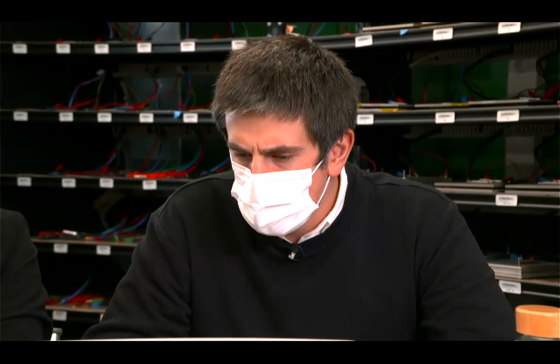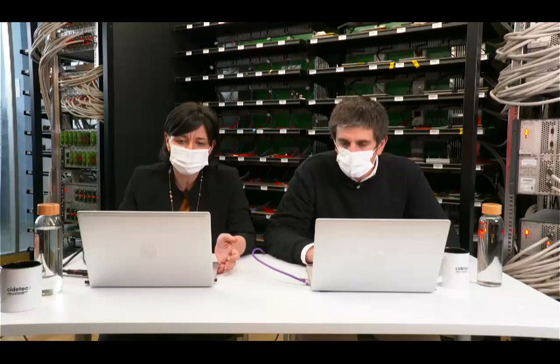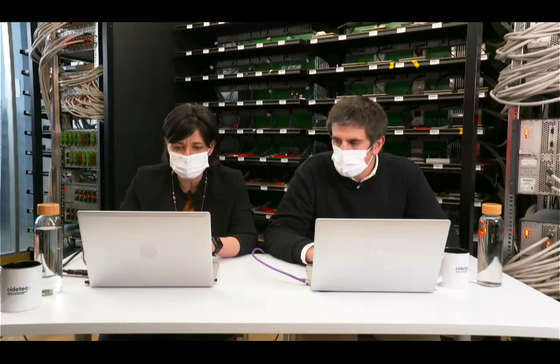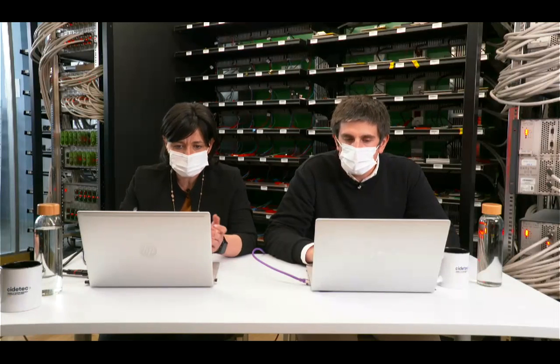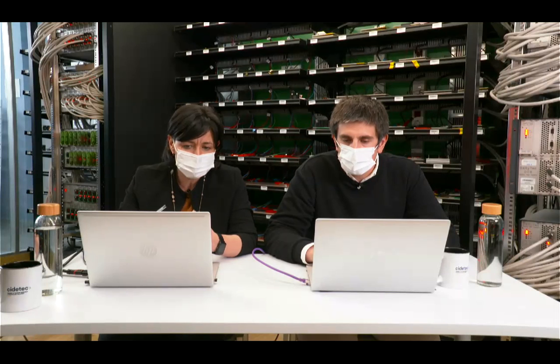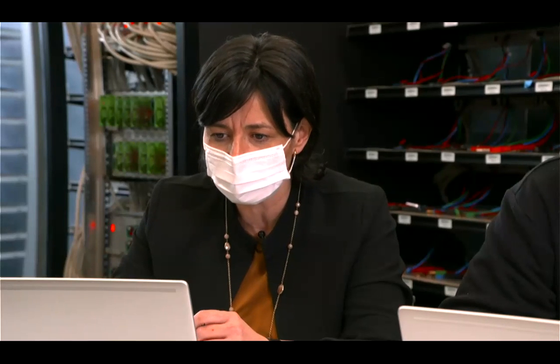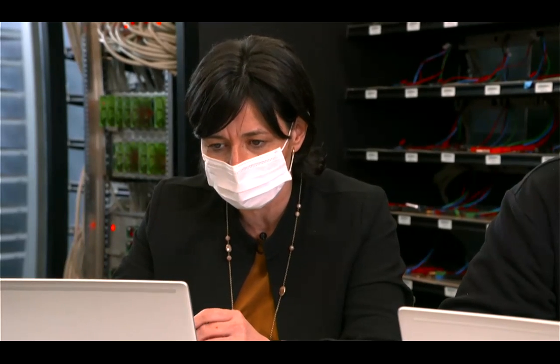Just to get an idea, for a standard electrode of 3 milligrams per square centimeter, something like that, this is quite standard for us, the coating speed will be around 1 meter per minute, and the drying temperature will be around 60 to 80 degrees.